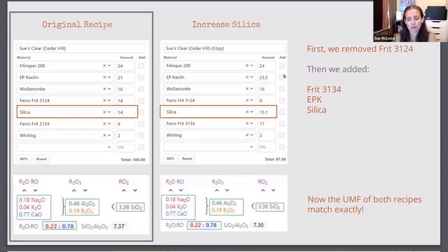So now I have a new recipe where the chemistry of the glaze matches the original. And now I can make this glaze. You can see Frit 3124 is at 0%. And now I have a glaze that is just with Frit 3134. So that is essentially how material substitutions work. I gave you the most complex example just so you can see that sometimes it's very simple, but sometimes it's a little more complicated.